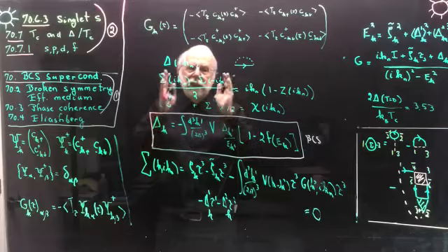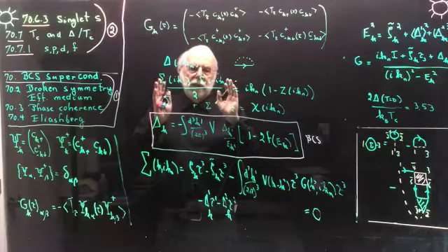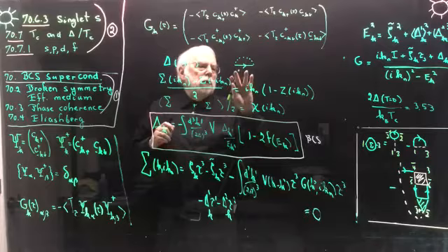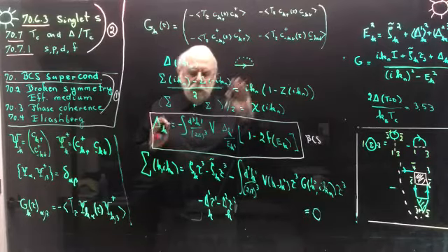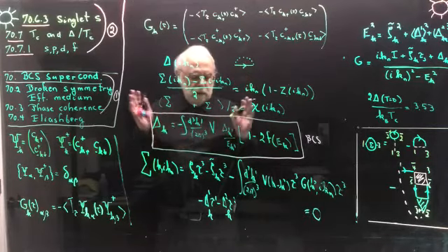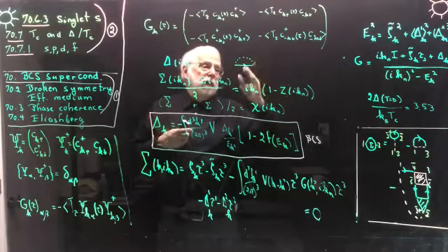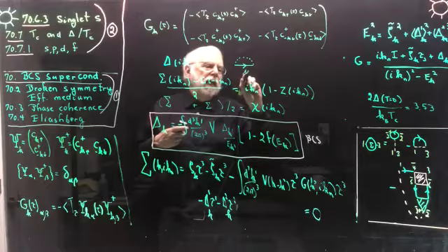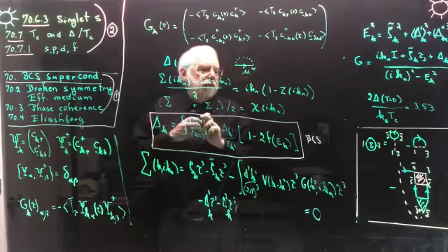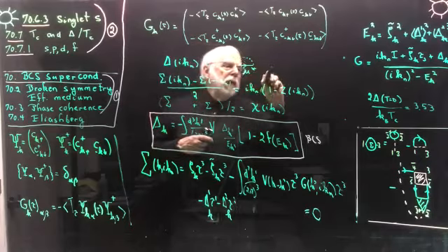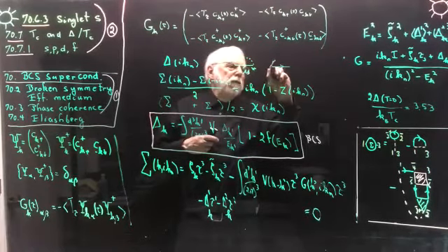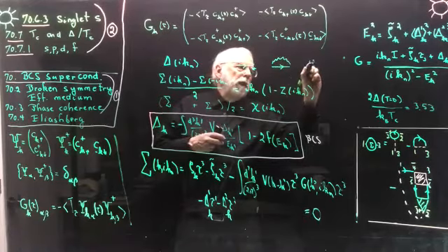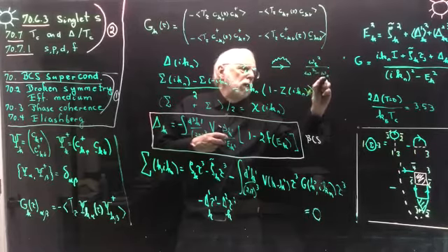We saw that attraction is limited to the Debye frequency. You integrate out all of the high energy processes, and that gives a much smaller Coulomb interaction, which ends up being described by an effective parameter called mu star. And then you get the real phonons here. So this is the phonon propagator, which we wrote as omega_q squared over omega squared minus omega_q squared.